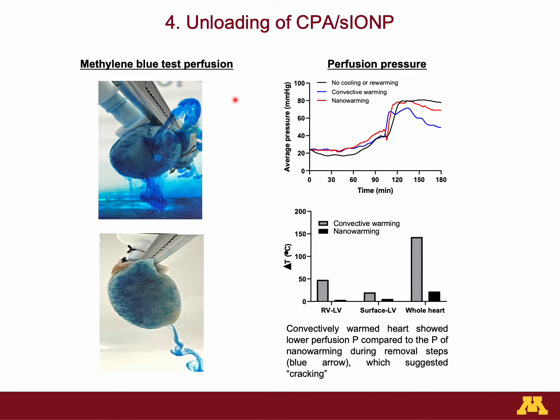After successful rewarming of the hearts, we unloaded the silica-coated iron oxide nanoparticles and CPA in a stepwise fashion. Convectively rewarmed hearts showed a lower perfusion pressure compared to nano-warmed hearts during the removal steps, which suggested cracking. In order to check for cracking, we added methylene blue dye to the perfusate and clamped the pulmonary artery drainage. The convectively warmed heart was leaking from the side of the ventricle, while the nano-warmed heart was intact, and dye was draining from the left ventricle catheter only.